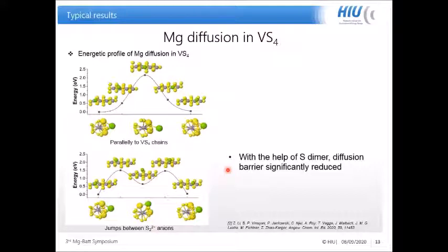We have also calculated the ion diffusion pathways in this VS4 structure, and here we have considered two scenarios. The first one assumes that the magnesium just diffuses in the channels, that is, parallel to the VS4 molecular chains, and this results in a relatively high energy barrier. In the other case, the magnesium could jump from one disulfur, or sulfur dimer, to the next. In this case, we have a much reduced energy barrier compared to the first case.